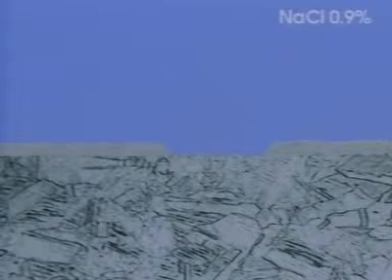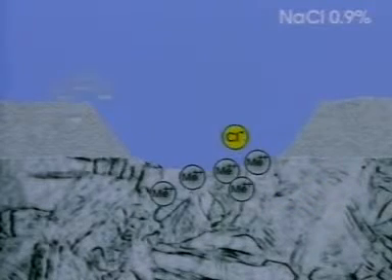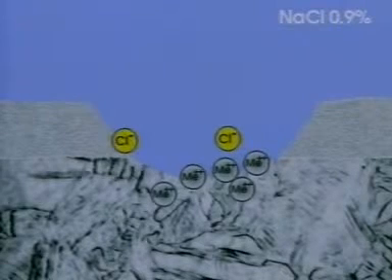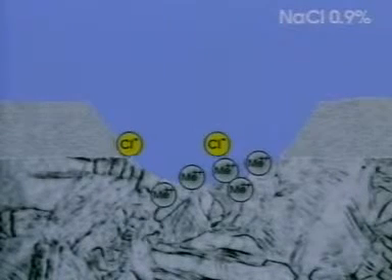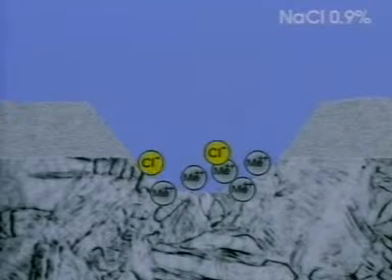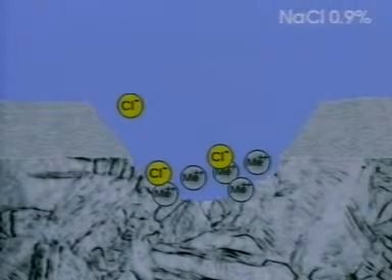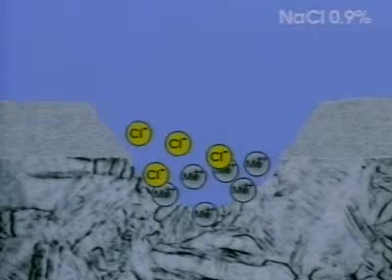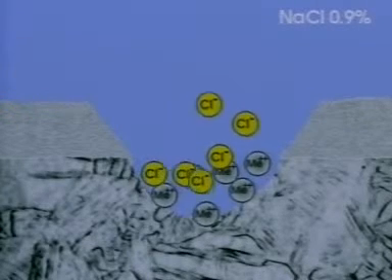Going back to the surface defect, the cathodic reaction occurs where oxygen is available. Metal ions form at the anodic site, creating a charge transfer. The charge must be balanced where there is a large excess of positively charged metal ions at the damaged site. To do this, the fastest and most available moving anions in chloride solution are the chloride ions themselves, which are sucked into the embryo pit. This produces an even more concentrated metal chloride solution.